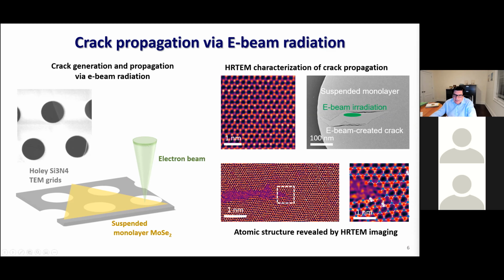What is exciting is that these are high magnification images at the crack tip, where we can see that the atomic positions are revealed under the right imaging conditions. And more than that, you can map the different atomic species. In this case, it's molybdenum diselenide. The blue is molybdenum, and the selenium atoms are the red. In this structure, even when there are distortions, you can reveal them very nicely at crack tips.